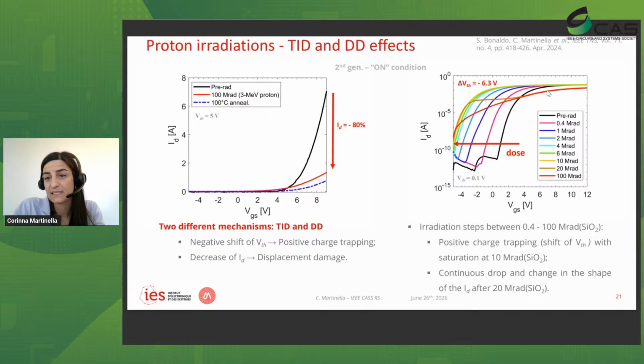And we can still see that there is some current, and this is due to the fact that below the bonding wires, those cells are shadowed, because now our protons have a penetration range of 57 micrometers, so they get stopped in the bond wires, and so those few cells were still conductive, and that's why we can still see some signal there.